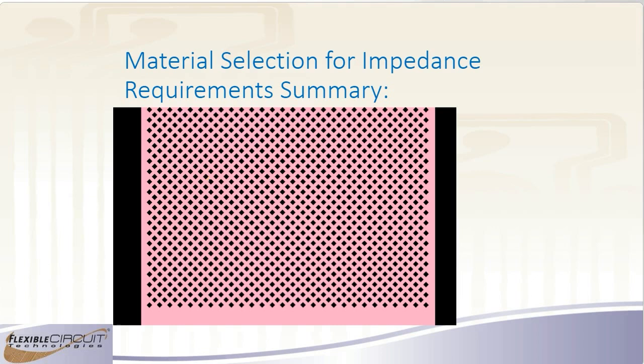Also, if you're going to use a crosshatch pattern, you typically want to run your crosshatching 45 degrees to the length of most of your transmission lines. If you were to turn it so that it was parallel or orthogonal to your transmission lines, there's a chance you could have some of those traces that are going to be coupled to a parallel line in your crosshatch and have a different impedance than the one next to it that could be just hitting the cross pieces. So by turning it 45 degrees, you end up with a more even distribution of coupling from those planes to the traces below.